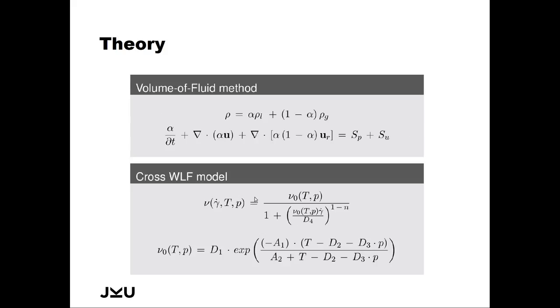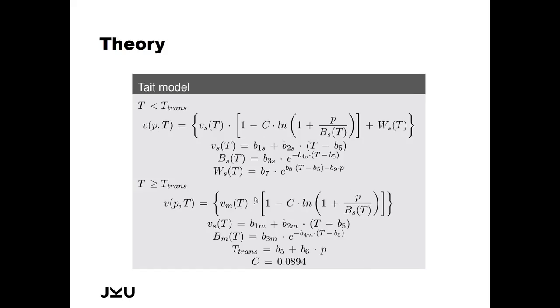It is of course a multi-phase flow where we use the Volume of Fluid method in its compressible version. We also model the non-Newtonian behavior of the material with the so-called Cross-WLF model, which is common practice in polymer processing. With this model we describe the shear rate dependence and the temperature and pressure dependence of the viscosity. Since the polymer melt is compressible, we use the so-called Tait model to model this behavior.